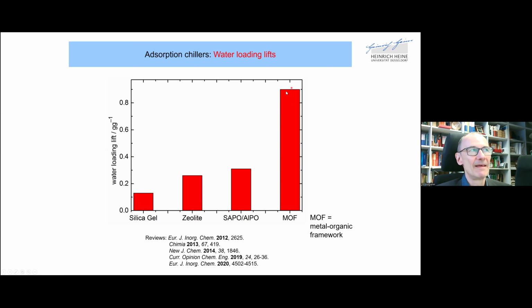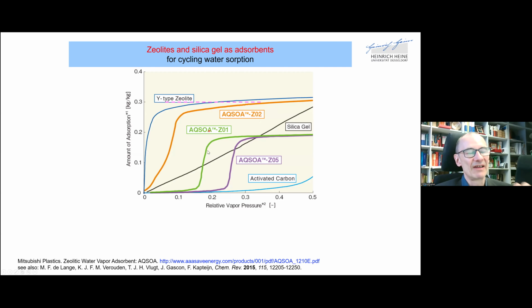So MOFs in a single cycle, or many MOFs or some MOFs, can take up a larger amount of water per cycle. And so that makes the whole process much more economical. Now, we of course have to look at another aspect which is important. One I just pointed out is the amount of water which is adsorbed, and that should be, let's say, above 0.3 gram per gram, or here it's kilogram per kilogram, but that is the same. So the existing materials, silica gel, or even modified zeolites or silica gel, which were developed by the company Mitsubishi, do not meet this target.